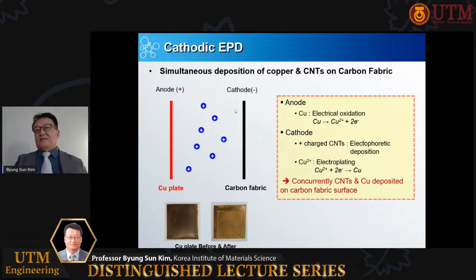In cathodic EPD, under an electric field, there will be electrical oxidation on anode. Then the copper element from the copper plate and the plus charged CNTs move toward the cathode and are simultaneously deposited on the surface of the carbon fabric. The picture of the copper plates below show dark copper plate before and the cleaner copper plate after the cathodic EPD process. Well, this method may be used to clean copper plate, although it may be a little bit expensive method.